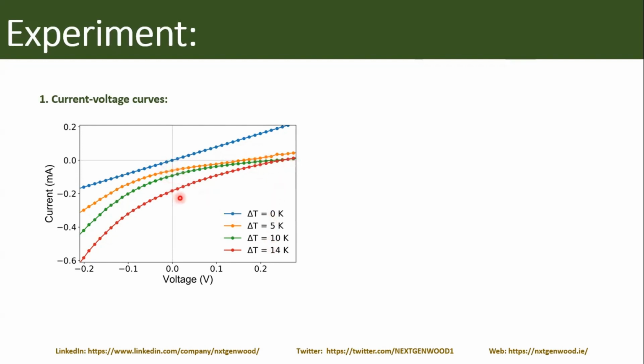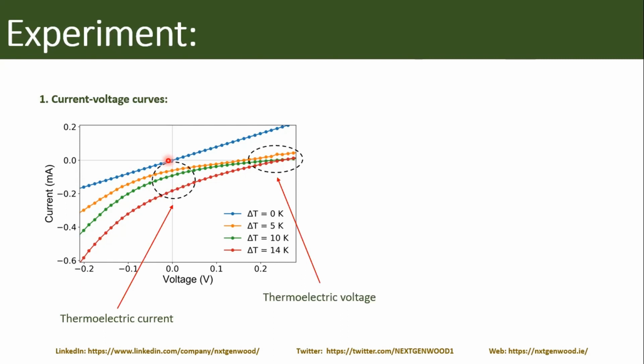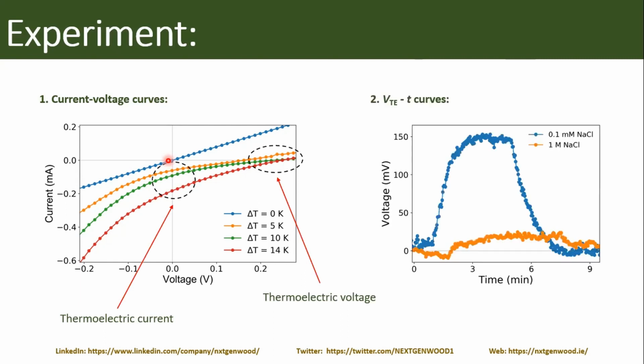And there is also some current, but later we realized that this current is not really good to measure in this way, because it is time dependent, and it depends on how quickly or how slowly you make the measurement. But anyway, we were able to see this effect. Later, we switched to something more similar to capacitor characterization, when we have this on and off of the temperature gradient, and then we have these charging and discharging curves.